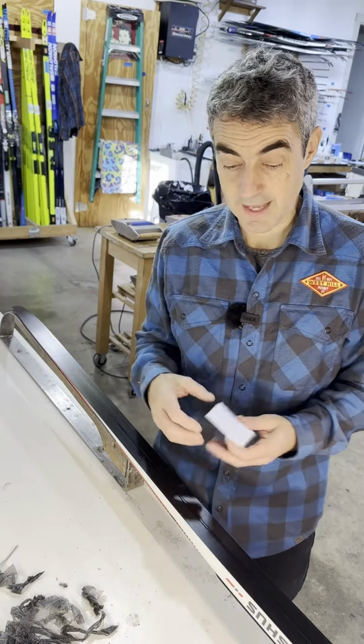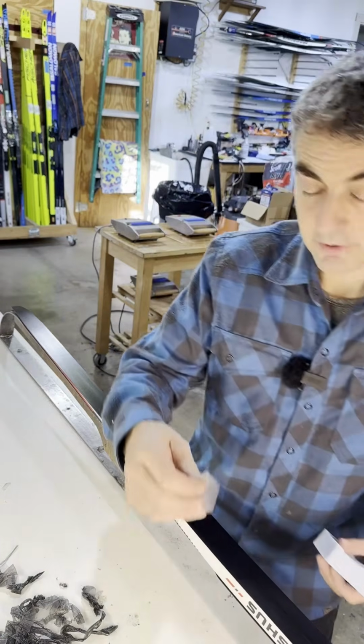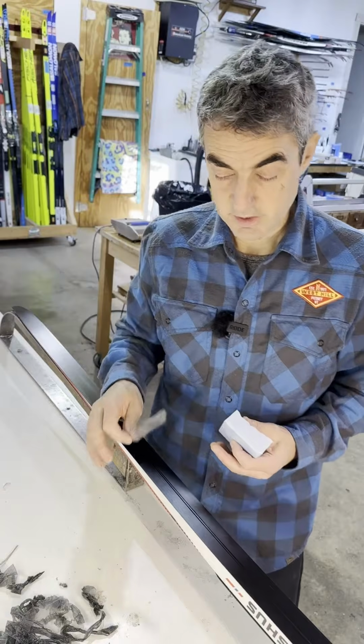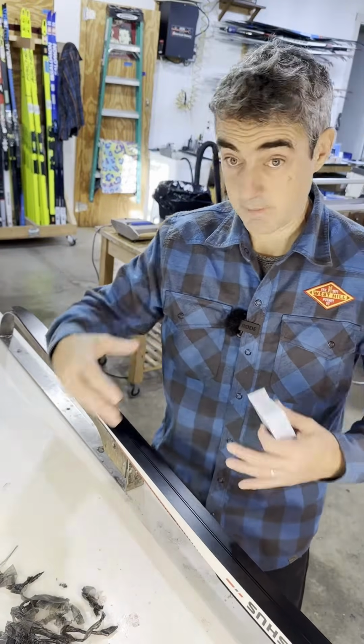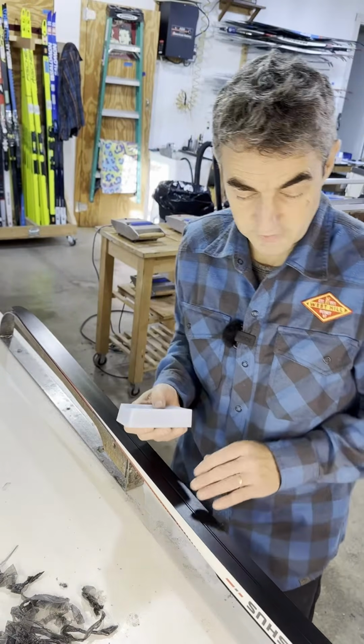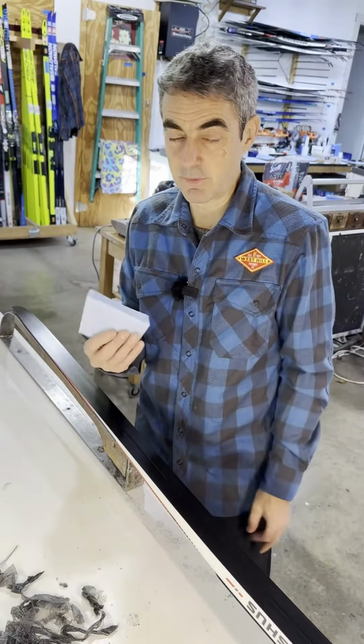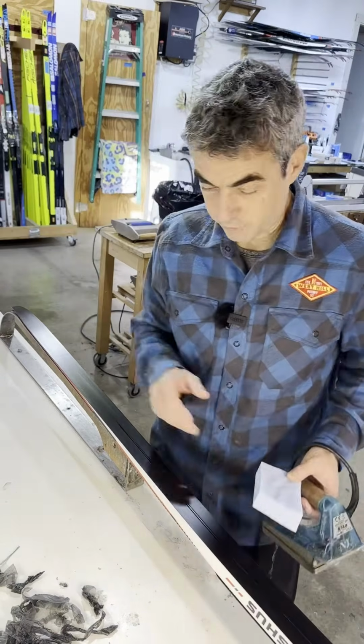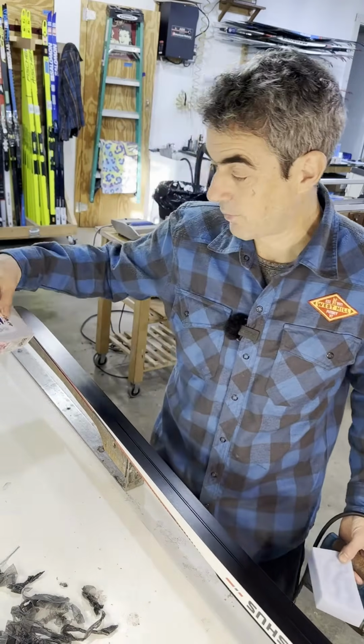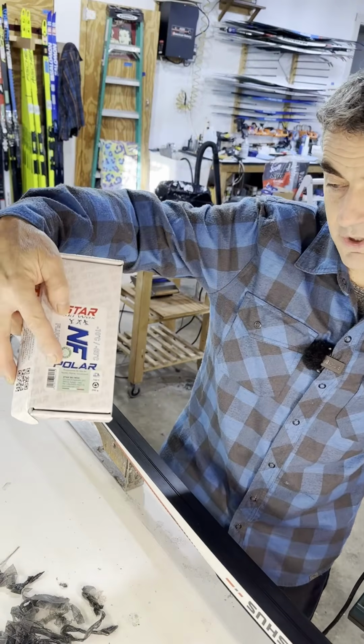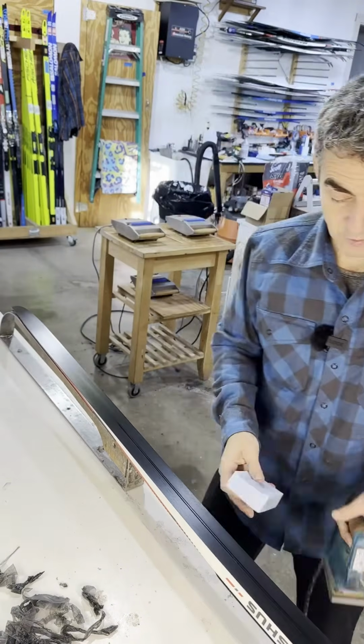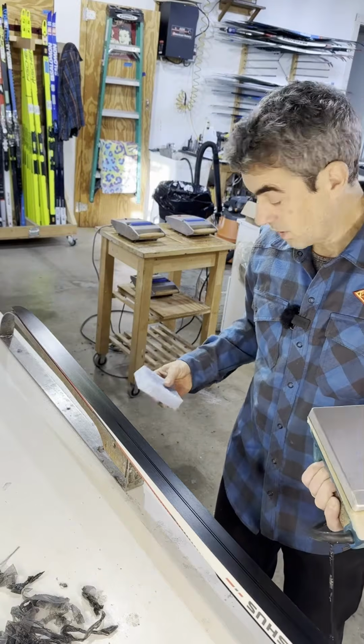We are going to put that base material up into that secondary glass transition temperature range, and the base is going to harden. This is our base hardening process, but it's also what you do anytime you put a really high melt point wax into the ski. It's really important to operate with the recommended iron temperature. Every wax company provides those recommendations. Okay, so we're at 150.